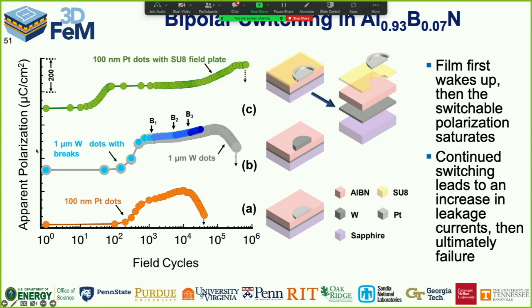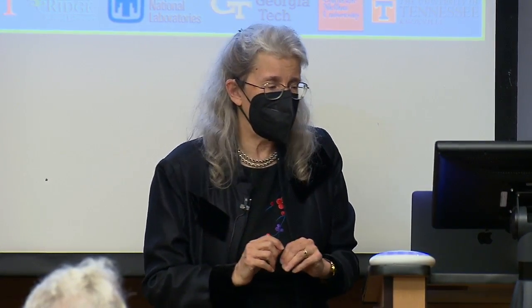And you can see what's happening here. So this is apparent polarization as a function of the number of times we rewrite it from poled up to poled down. With 100 nanometer platinum dots, you wake it up, that's good. The polarization is stable for a little while and it starts creeping up. That's not physical, that's all leakage. And then the apparent polarization starts to plummet. That's associated with the fact that we're actually, in this case, blowing up the perimeter of the sample, and we fail it into an open circuit condition so we can run the next cycle, but not what you really want to do.